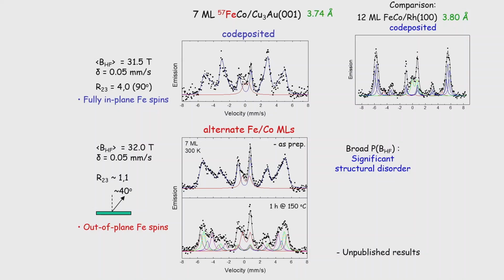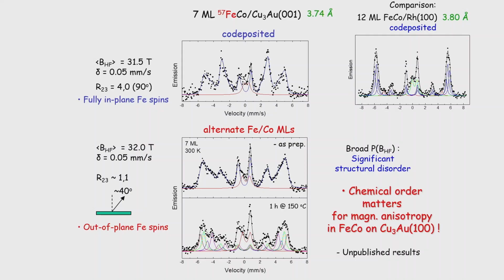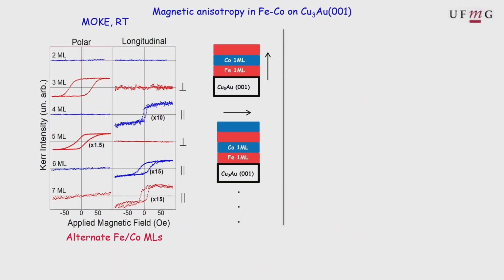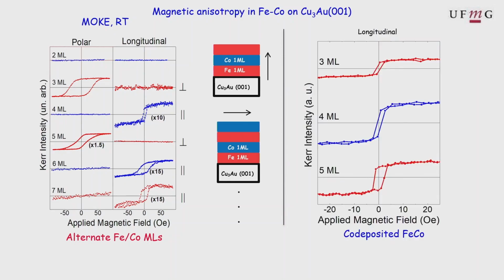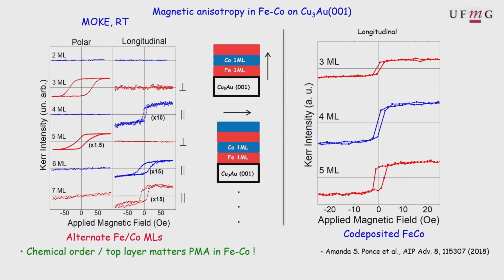We are not able to do a 1 monolayer iron-57 Mossbauer spectrum in situ because of the time of measurement. It does not make sense in our system. We see that chemical order matters for this system, but we cannot do it by Mossbauer. Then what we did is by MOKE. What we see here by MOKE is that every time we grow one monolayer of iron, one of cobalt, one of iron, cobalt, the spins change. You will see that the spins are changing from in plane to out of plane every one monolayer of iron cobalt, okay? If you put alternate monolayers. And if you do the same by co-deposition, you see always in-plane spins. This is a very interesting system, very delicate. The magnetic anisotropy is a very delicate balance in the system, but we see that the chemical order matters for the anisotropy in this system, but the one-monolayer resolved Mossbauer investigation is still missing.